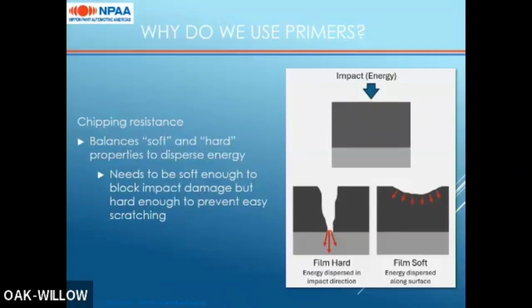So in this infographic, we have the impact coming down and hitting your coated surface. If your film is too hard, then that energy is dispersed in the direction of energy impact, which then allows for deep defects to occur all the way down to the E-coat or steel layer. Whereas if your film is soft, ideally optimized, that energy is then dispersed along the surface, so it just creates a small scuff, and your E-coat and steel surface stays well protected.